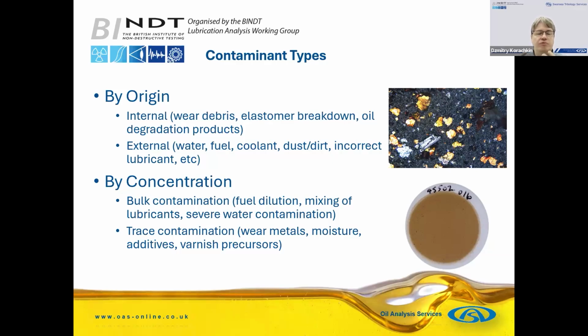But we sometimes need to look for contaminants which are present in very, very small quantities, concentrations. So trace contamination, this can be wear metals, moisture again. Some systems are very sensitive to water content, so being able to detect it at a very early stage, at very low levels, like we were saying earlier, parts per million rather than percentages, and sometimes even 70 parts per million in an application may be considered too high. But also ingress of additives as an indication for different lubricant getting in, and the varnish precursors as well. They're present in small quantities, but they can cause various problems.